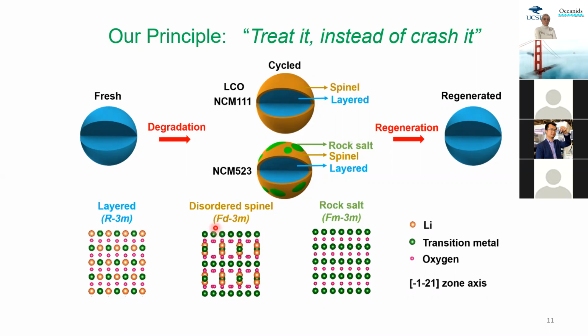They have some lithium ions and nickel ions, they migrate into each other's position. They form new phases, and these new phases are not favorable for lithium ions to travel, to transport between two electrodes. So you are going to have a higher resistance. You are going to lose the amount of lithium that is going to be reversible, okay?